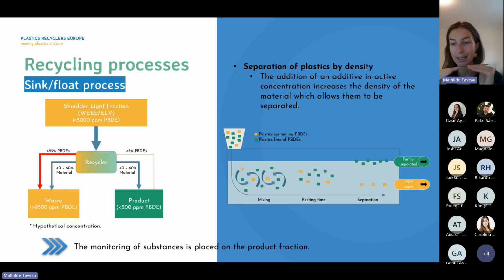So it's going to change the density of your plastic, and instead of being at the same density as your intrinsic polymer, it's going to be at a higher density, meaning that if you put it in a bath at a specific density, then it's sinking. So then you can really separate the plastics that are sinking, that would contain some brominated flame retardant, from the ones that are floating, that will not contain those substances, and therefore can be recovered afterwards. The plastics that are sinking and that are containing the substance are then sent to disposal.